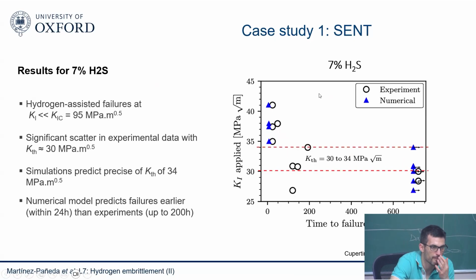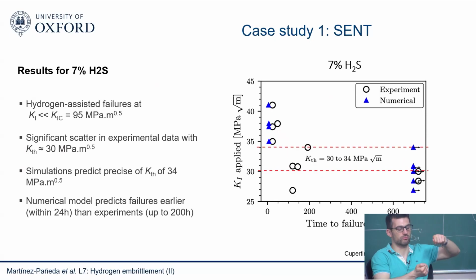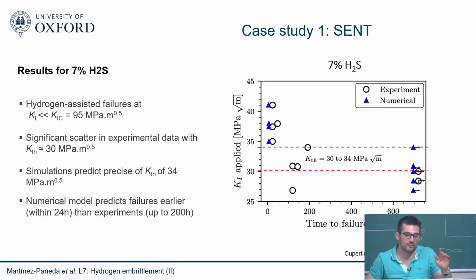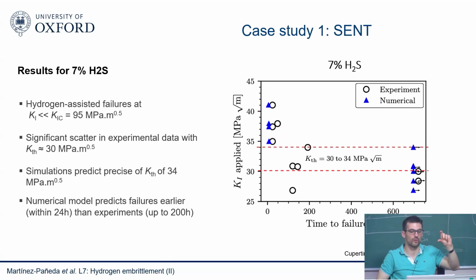What is the difference between KIC and KTH? It's basically a constant load test, so whenever your crack stops, you can measure the K that corresponds to that crack length and that applied load. And that gives you the KTH. But I think KTH is defined as the load below which you will not see any damage whatsoever. Above, you will see it. So these are the experiments that fail versus not fail. Then they use that for design. So they say, okay, my KTH is 30, I make sure that in my component I never exceed 30.